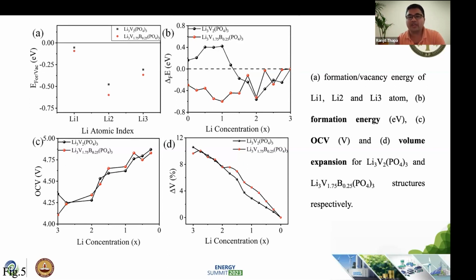So why is it happening? Then we showed that it is happening because of the vacancy energy. So we are dealing with the vacancy energy and also the oxidation state of the vanadium. If we change that by doping with boron and we correlate that, then you can easily increase the lithium extraction from the cathode.